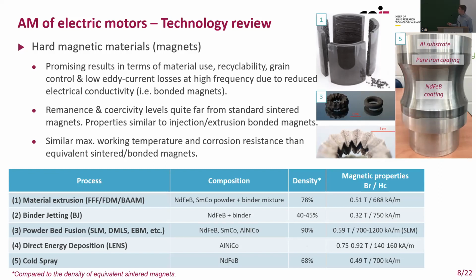There are also some promising results regarding low losses in the magnet materials at high frequency due to a reduced electrical conductivity. But in general terms, especially regarding the remanence and somewhat the coercivity, levels are quite far from standard sintered magnets. For the moment, the properties of the magnets produced by additive manufacturing are more similar to those of bonded magnets produced currently with traditional techniques of injection or extrusion.